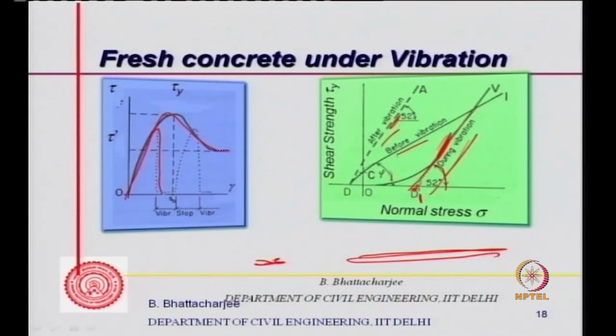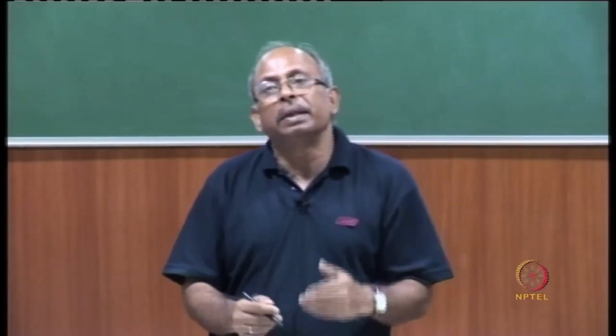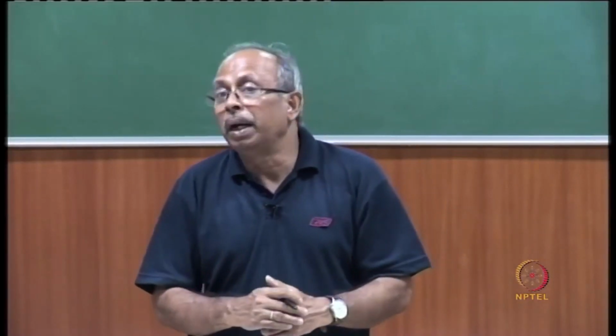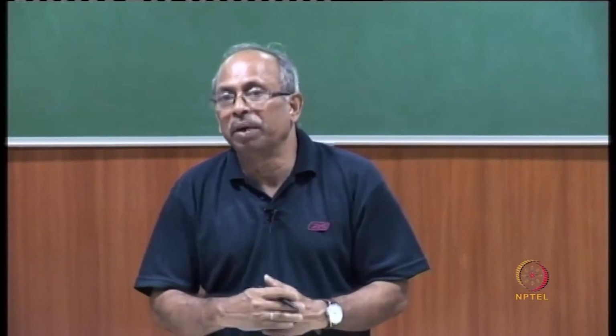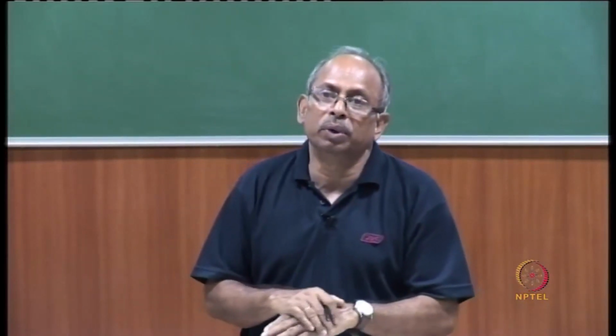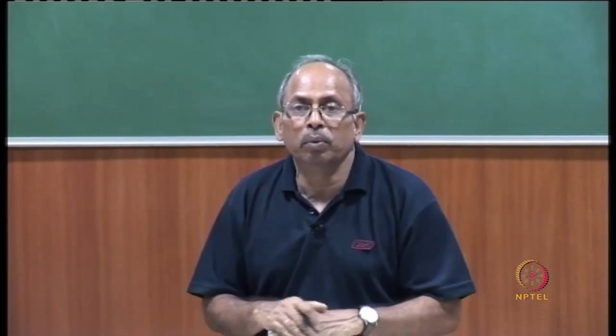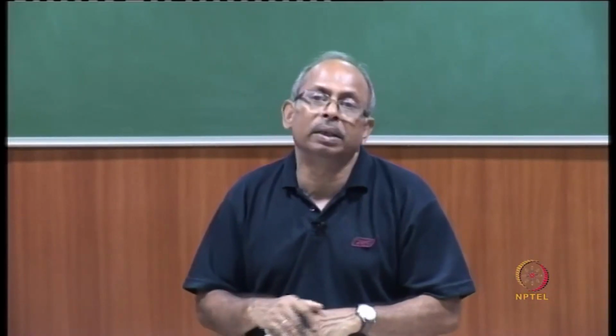During vibration, you start vibrating, yield shear stress comes down very significantly, and then you stop, again it re-establishes itself, and that's how it is. So basically, when you are vibrating, yield shear stress comes down. Therefore, particles can move. Movement due to the shear force can occur.